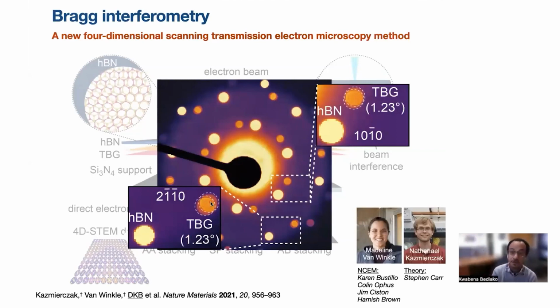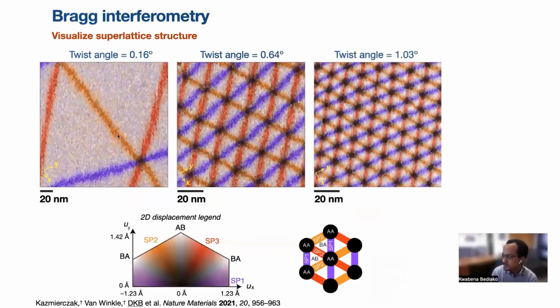And so we end up with maps like this, where at each pixel, the color assigned to that pixel gives you information about the X and the Y component of the displacement vector of the sample. It gives you a quantitative visualization of the Moiré superlattice, so that at each point you see the direction and the magnitude of the displacement vector between one carbon atom and the next. What you'd expect if there was no relaxation at all in the system would be a gradual transition between, say, the white to the orange, the white to the red, and to the purple as you went around the sample. But instead, we see these very sharp transitions, almost like domain walls, which is indicative of some deformation to the rigid Moiré lattice.